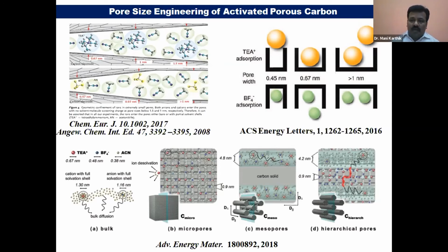That's a very important parameter, because if you see the ionization of any material, for example, an aqueous base like KOH, it has K plus and OH minus, so 2 ions. This is what we call the bare ion. But if you have water molecules, there is a solvation effect, so the ionic size is bigger. The bare ion size is smaller than the solvated ion size. So it has different types of ionic size. Only these ions enter the pores, then they are adsorbed.